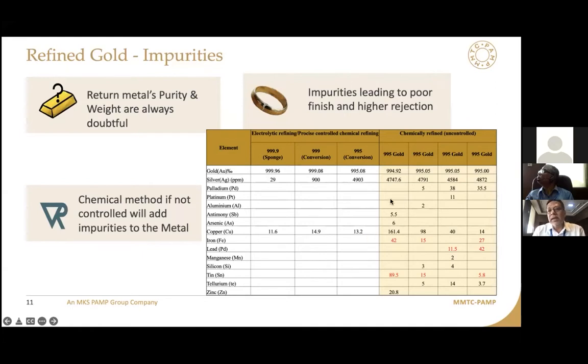We also did certain experiments, and we also tested some of the golds which are coming in the country. We did find in certain cases when we did a chemical refining experiment, if you do it in a very controlled way, we could reach this first column with a limited amount of impurities. But if we do not refine it in a controlled way and we refine the whole thing, some of the impurities do get precipitated. So most gold which is refined chemically may contain impurities like copper, which is okay. Copper may not result in a lot of problems.